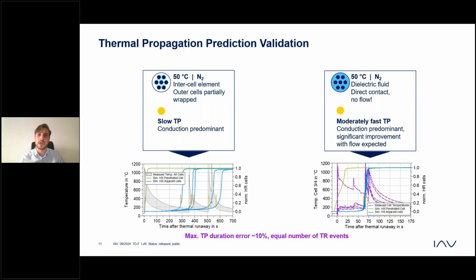In the right case, we have a totally different material. So we have here a fluid. The cells are immersed in a fluid, and what we see in the experiment, so that's the purple curves, is that the central cell is first seeing the runaway, and then the outer cells are seeing this runaway almost simultaneously.